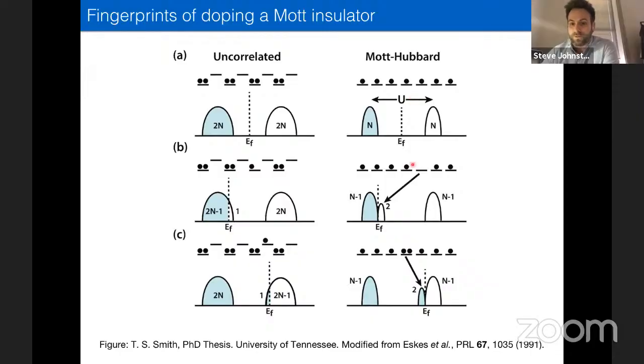When you dope the system, though, you can do the same counting argument, and what you find is that, again, there's n-1 ways now to remove the electron, if I've taken one electron out of the system already. There are n-1 ways I can add an electron, again, at an energy cost U, but I also introduce 2 ways that I can add an electron, either a spin up or a spin down to this empty site, and that costs me almost no energy relative to the occupied states. And so what happens is you get this quasi-particle-like spectral weight forming here, which pulls its weight equally from the upper and the lower Hubbard bands. And you expect the same thing to happen with electron doping. It's just which Hubbard band your quasi-particle peak gets tied to shifts.